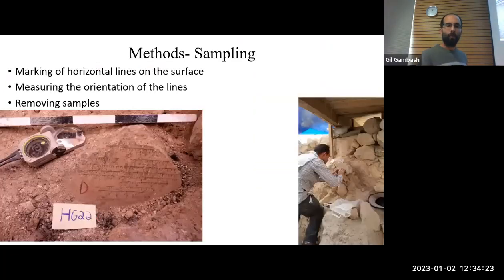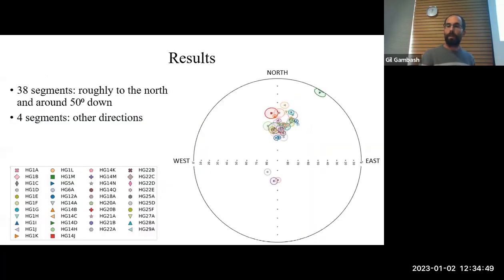What I did was mark lines on them before they were moved, when they were still in their original, collapsed position. I measured the direction of every line and the orientation of the surface, the vertical angle of the surface. Then I removed them, took them to the lab, cut them into little pieces, and measured the direction of every one of them. And these are the results. You can see 38 of these segments that I measured gave us directions that are clustered around north and down.